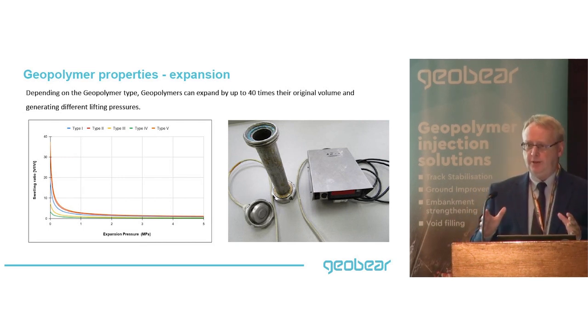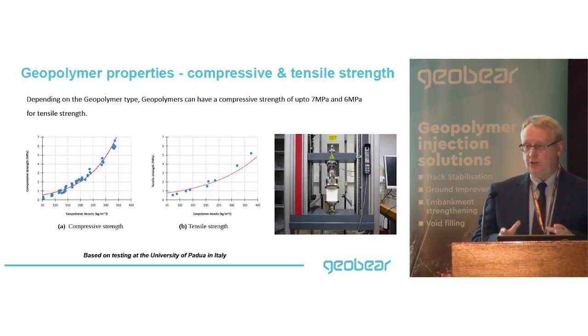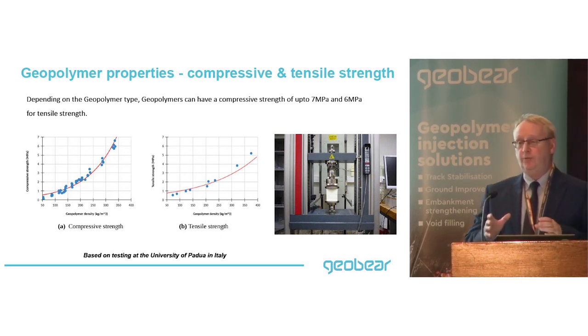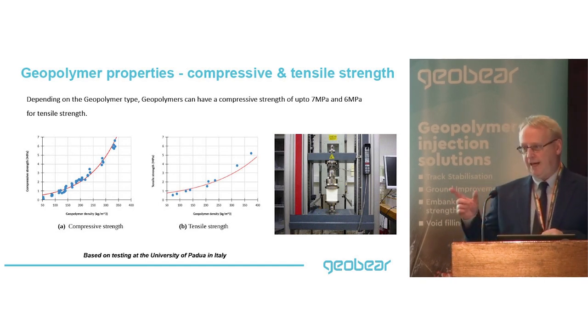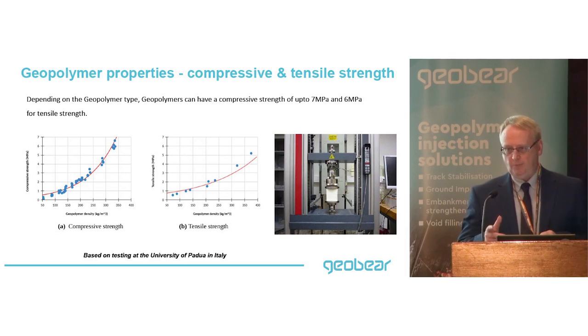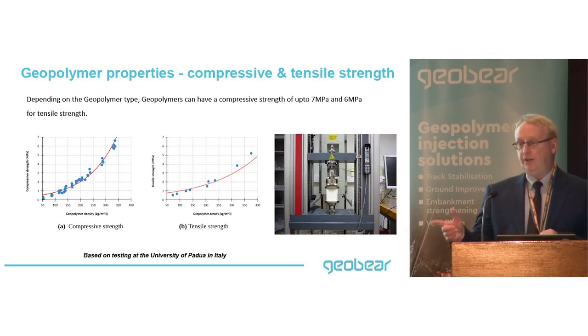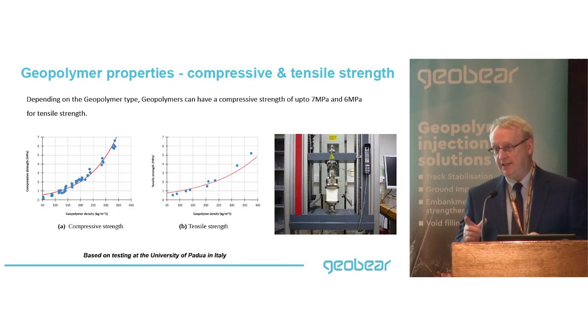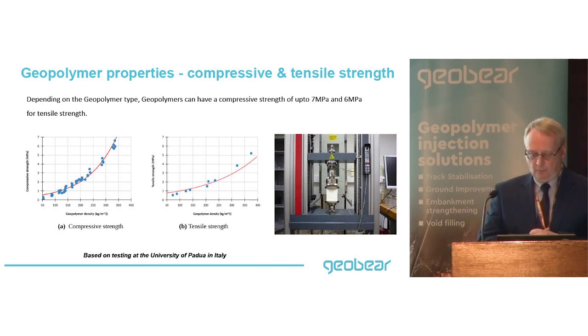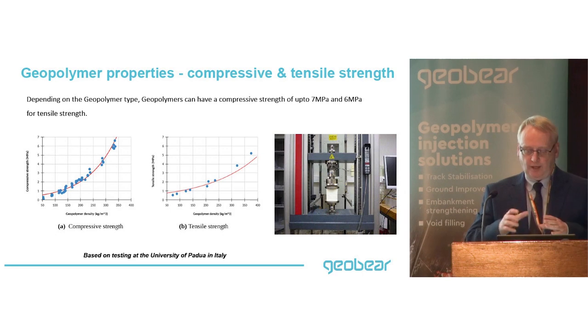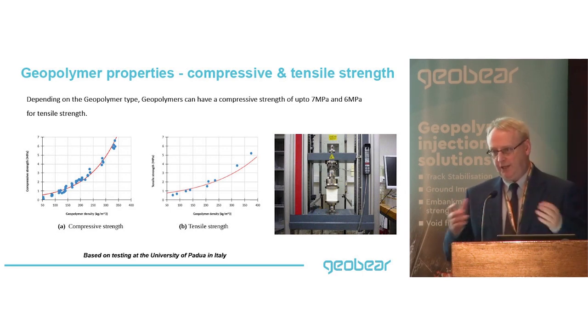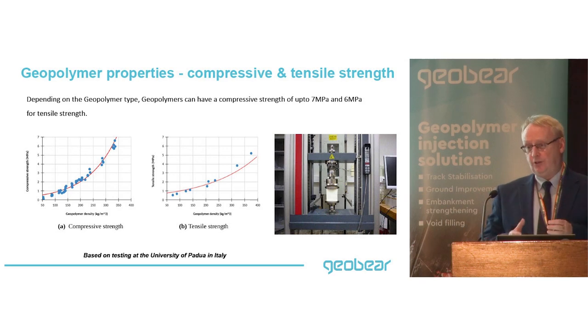So how strong is geopolymer? The strength is a function of the density. As the density of the polymer increases, the compressive strength and the tensile strength both increase. The two examples you've got out there - one is a low-density polymer, and one is a high-density polymer. They will both have different compressive strengths as a function of that density. What is also interesting to note is the compressive strength and the tensile strength are fairly similar at the same density, so it's not like a concrete which is strong in compression and weak in tension. These are strong in both directions, if you will.